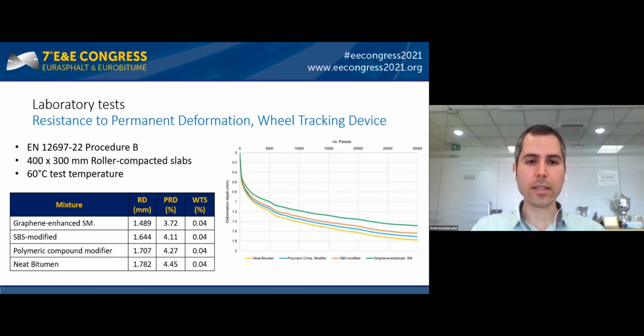The second test during the lab scale investigations was permanent deformation. Here you can see that according to this table, the permanent deformation for the mixture containing the graphene enhanced super modifier was superior when compared to the other tested mixtures.